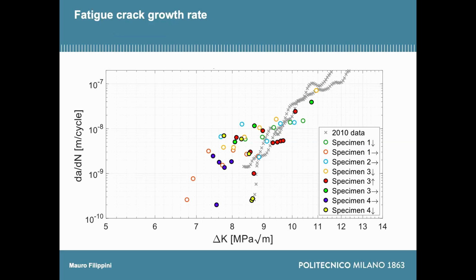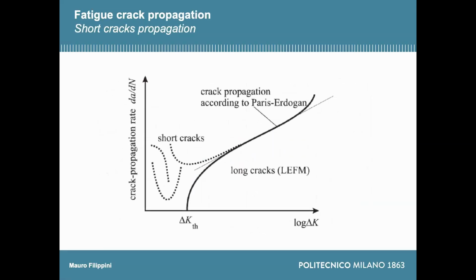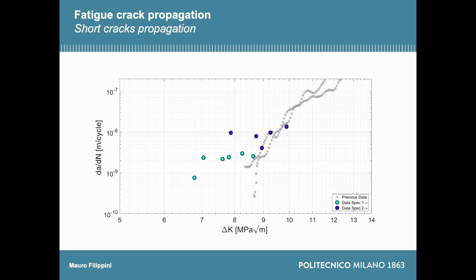So you have a marked effect of the microstructure on the fatigue crack propagation in this case. And you can observe that the new data shows an increased propagation, and then a reduction, and then an increase of the crack propagation rate, and again a decrease, until you reach a definite long crack threshold. And if you want to propagate the crack definitely, you have to increase the delta K up to 10, 12 megapascal square root meter. Okay. So the rationale is depicted here.